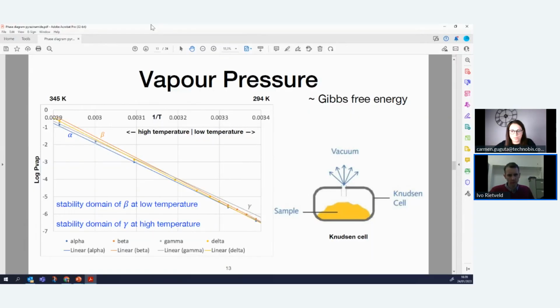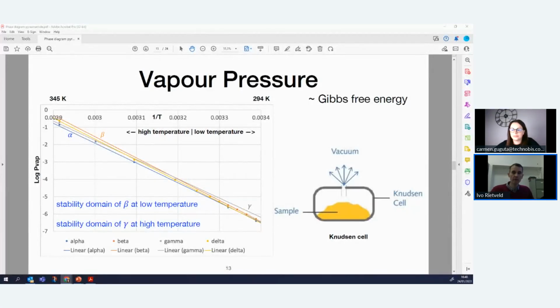And Ivo? Yes, one thing is, so we have the vapor pressure here. This is done with a Knudsen cell. I will not go into the details of how that is exactly measured. What is more interesting to know is, first of all, the vapor pressure. So the vapor pressure allows you to determine the Gibbs free energy basically directly, because the vapor pressure is a direct reflection of it. And the graph there at the top, you have to pay attention. It is a function of the temperature, but it's the inverse temperature. So on the right side, we have room temperature, 294 K, which is about 20 degrees. And on the left side, we have 345 K, which is about 70 degrees Celsius.